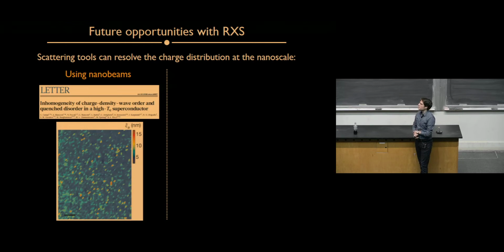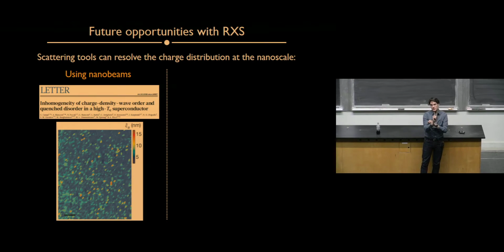And one of them is to do diffraction, or resonant diffraction, so look at electronic orders, but now with an X-ray beam which has been focused to a few tens of nanometers in size, using special diffractive optics that can do that. Let's say we have those optics. Actually, we do have those optics. So we can focus the X-ray beam down to a few tens of nanometers.